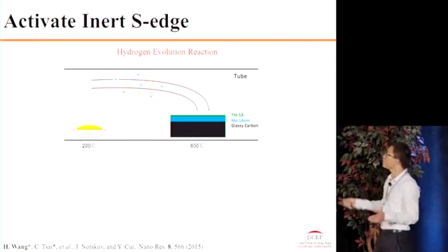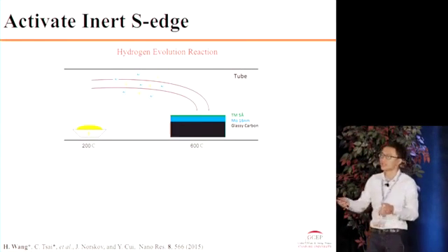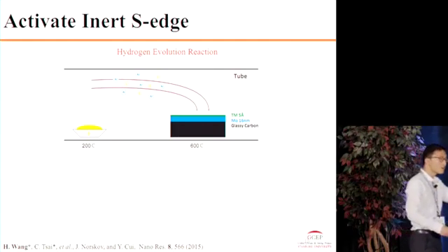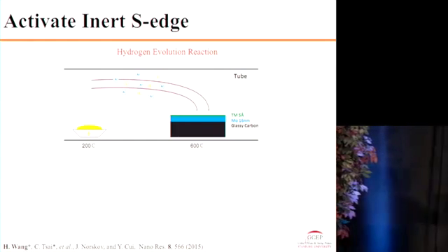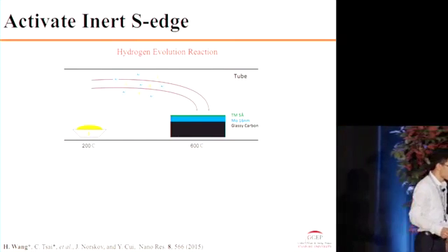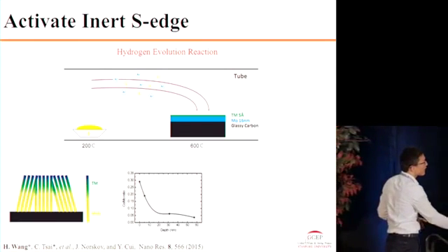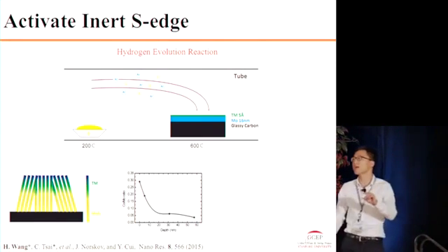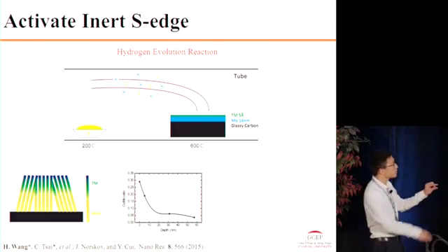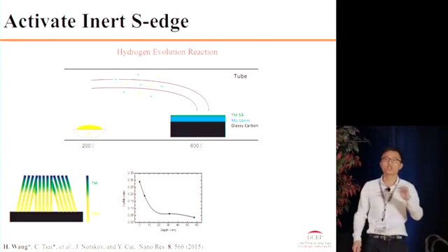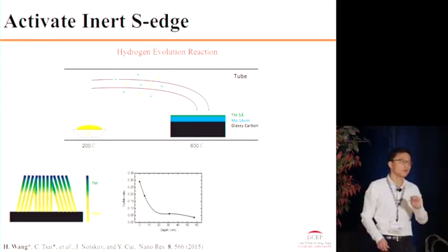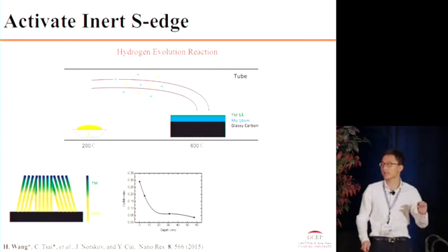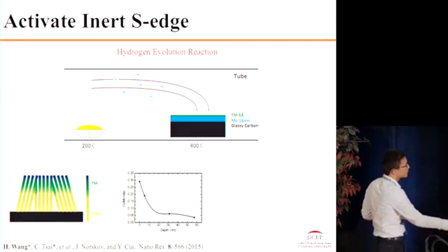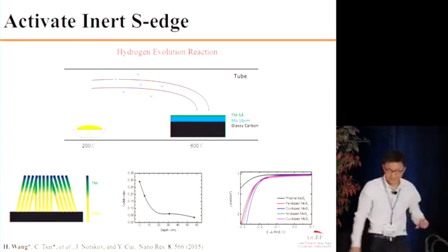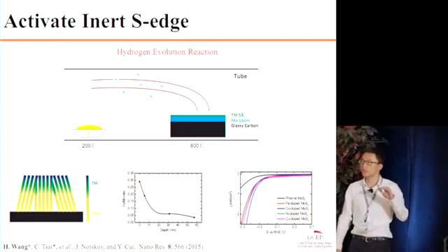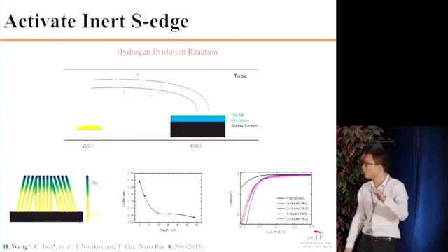A very easy way for us to achieve that is to evaporate an additional very thin layer of transition metal on top of the molybdenum and do the sulfurization at the same time. You can see that the concentration of these transition metals will focus on the very top surface, ensuring that most of the sulfur edge sites can be doped with these transition metals. And as we can see, the catalytic activity is indeed doubled after the doping process.